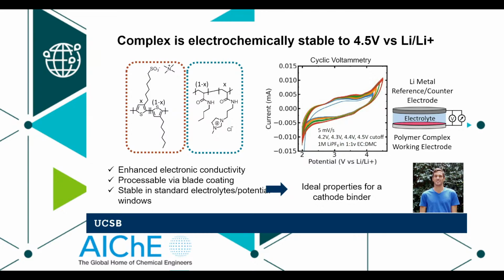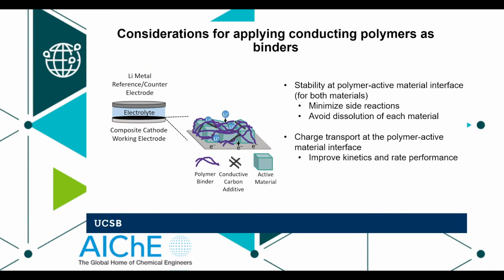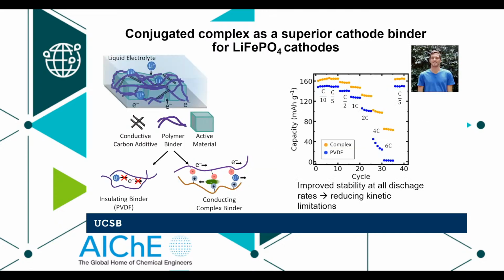for a cathode binder. So what we're going to do is incorporate it with that LFP as well as the carbon additive. We actually don't need the carbon additive because the polymer is so conductive, but in order to do one-for-one comparisons, we're going to always throw it in. And we're going to hope that it improves both the kinetics and the rate performance. So this is what just a first attempt try looks like.